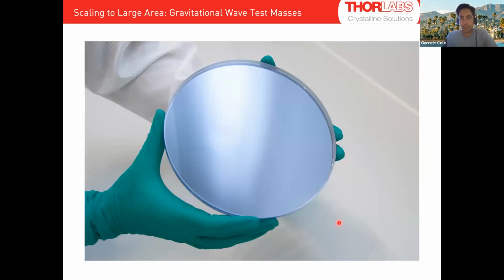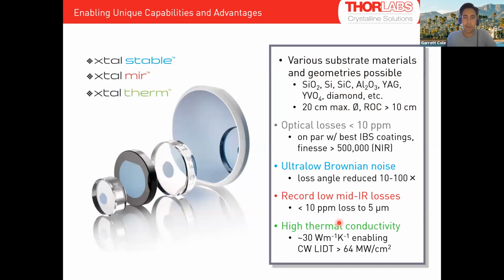Here's an example of a 20 centimeter diameter test bond that we ran to demonstrate that we can do defect-free transfer at up to 20 centimeters. Again, that's not big enough for LIGO, but it's a step towards that to justify these sort of large investments. I'm now going to move on to the next topic, and this will be much shorter, which is showing the record low mid-infrared losses.